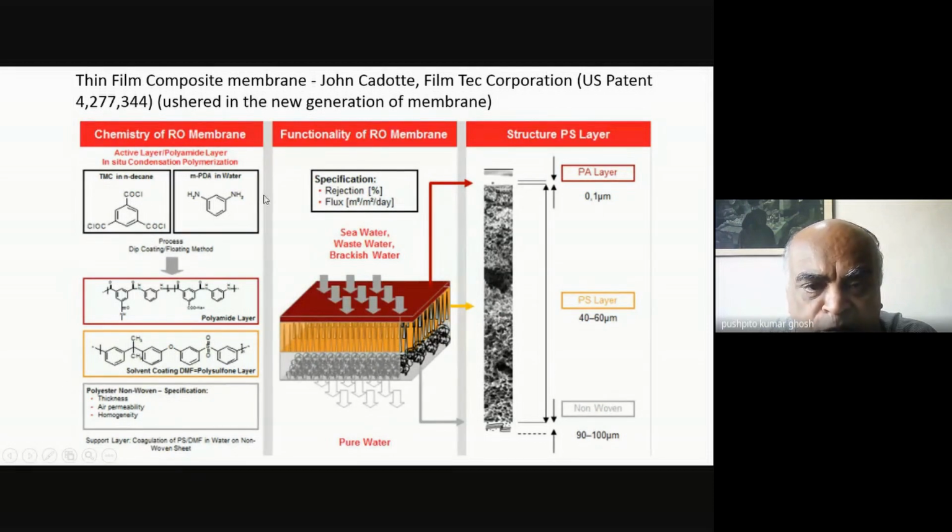So some amount of this diamine, metaphenylene diamine, sticks to this polysulfone. So it gets in. Then since quite a bit of water gets in, you try to remove most of the water, maybe with the help of an infrared lamp, which is put